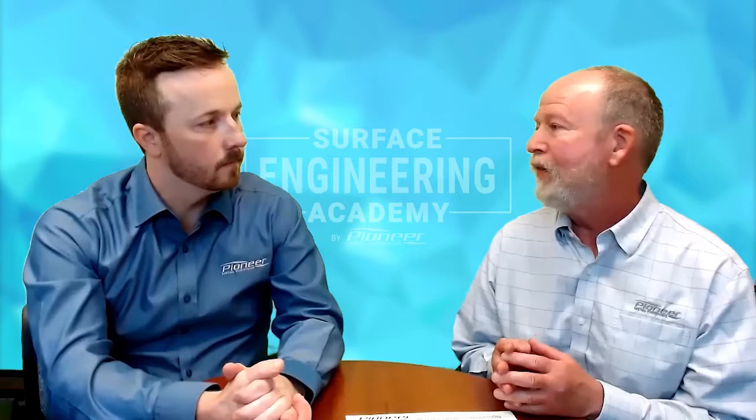Steve, in addition to dye acceptance into the base coating, talk to us a little bit more about how light impacts color consistency, the overall UV shift of color over time, and durability of the dyed coating. A couple of really important factors for anodizing durability and light fastness of the dye are how thick the coating is. A thinner anodized coating cannot hold as much dye material and will not hold up as well to light without fading and discoloring.